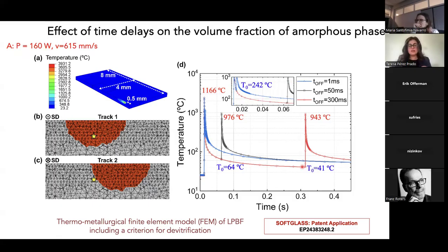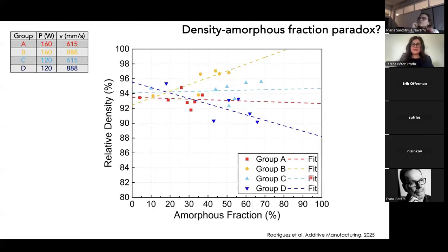So, of course, the introduction of time delays allows the sample to cool down, and then in the heat-affected zone, the material there spends less time at high temperature, so there is less likelihood of crystallization. And this is why time delays help to increase the amorphous phase. But then let's go back and see how we are doing in terms of this density amorphous fraction paradox that we wanted to overcome.